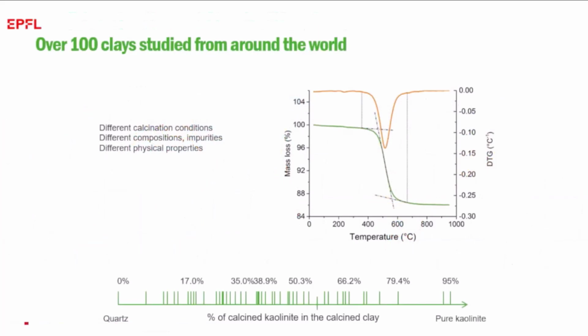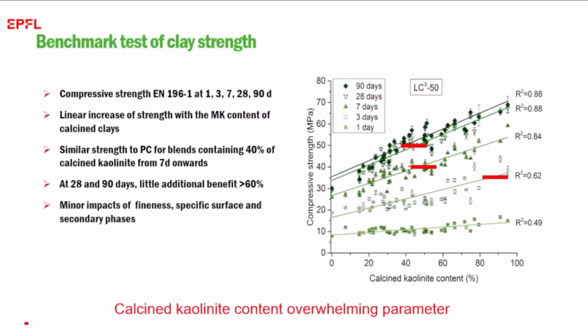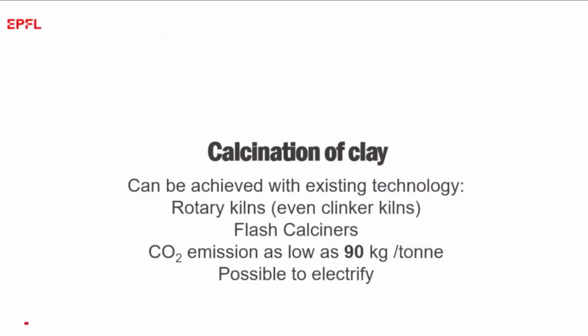We can quantify the kaolin very easily by looking at the weight loss in the range 400 to 600, and we can see that the strength development correlates very closely with this kaolinitic content. The red bars here are the reference Portland cement. So if we want to have a similar strength at 7 and 28 days, we need a kaolinitic content of somewhere around 40%. But even some of these clays in the range down to 30 are doing pretty well.